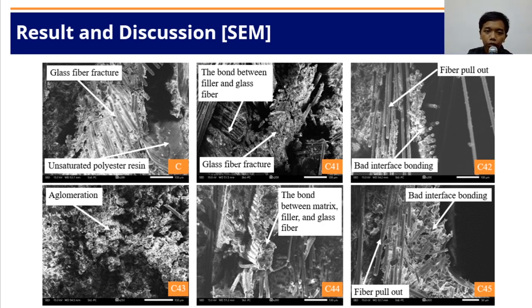In the C42 and C45 composites, it can be seen that there is fiber pull-out in most of the fracture area. This phenomenon indicates that the binding ability between matrix and fiber is still not good. Then, the filler distribution in the composites looks poor, causing many cavities which lead to a decrease in the ability to receive impact load.